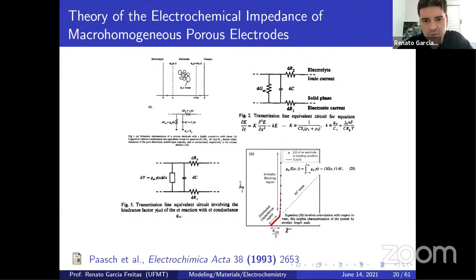And electronic current is orders of magnitude faster than ionic current. An ion getting inside the pore cannot compare with the electronic structure, like in nanotubes, where we have ballistic conduction like this one. So these models were further generalized by including an arbitrary time delay called hindrance. This term here is called hindrance. All this part here is hindrance, like G of the charge transport process at the pore surface.